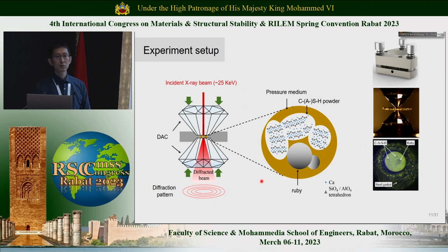So what we did with this synchrotron technology is that we want to use the super high flux X-ray to be diffracted by our CSH, when the CSH is in a condition that is hydrostatically loaded to a few gigapascal.